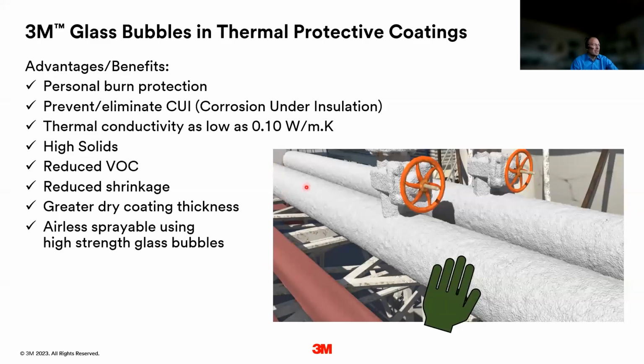And last but not least, since this coating is directly applied on the pipes, on the valves, whatever, in case of condensation effects, there's no water that can accumulate under the insulation, and therefore it prevents what is typically referred to as corrosion under insulation, because there's just no gap between.